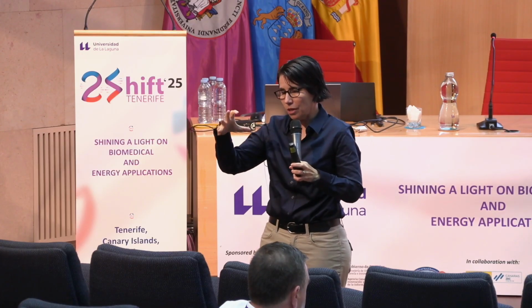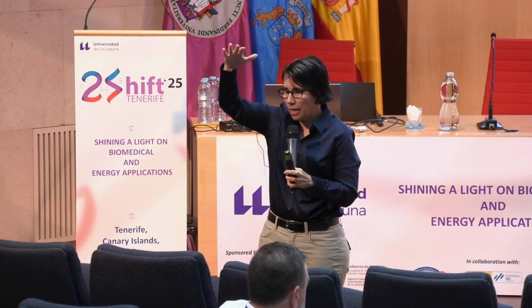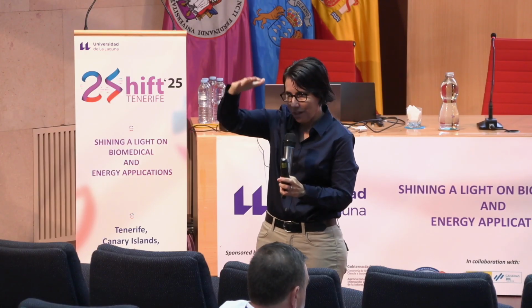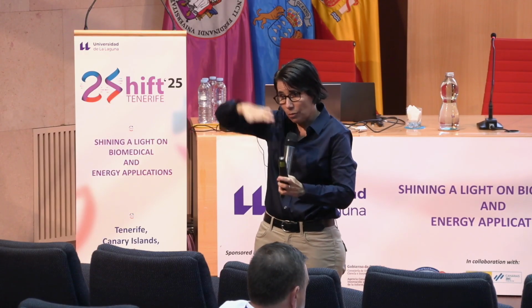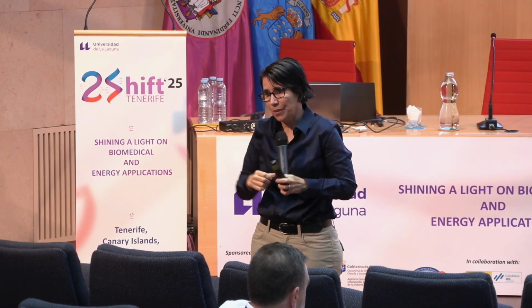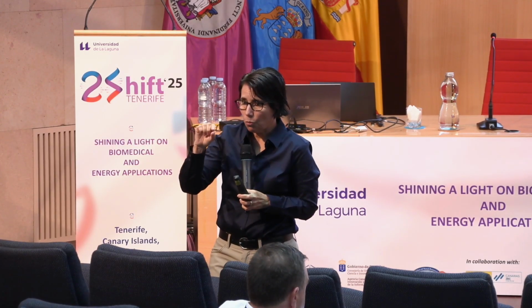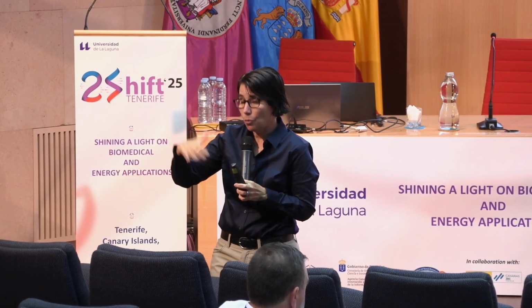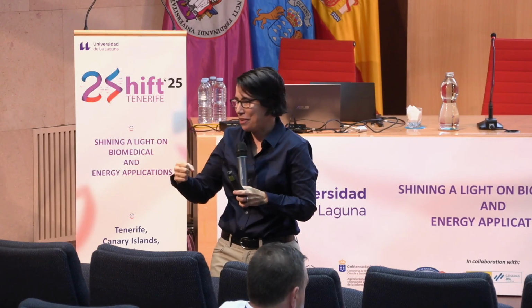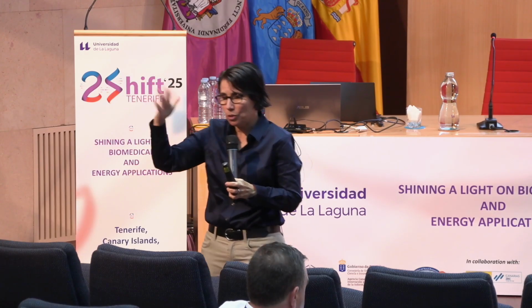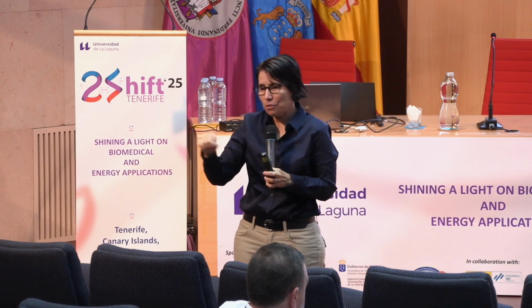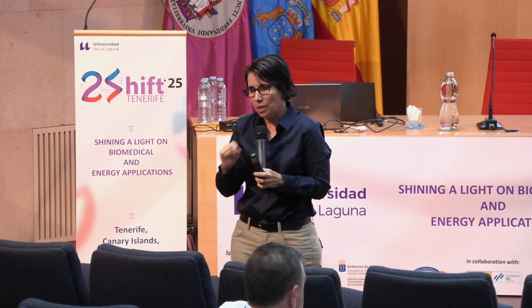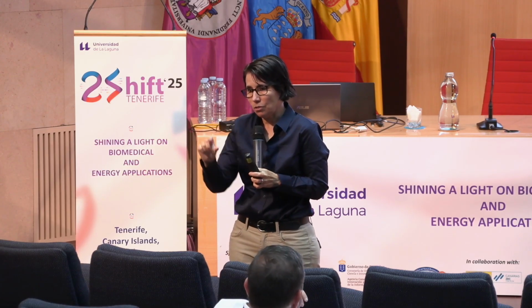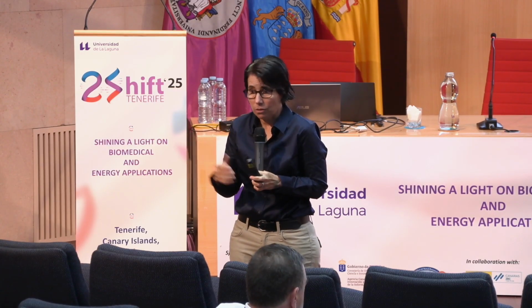If you have a layer of nanocrystals and do this ligand exchange, even if you have a film, you can see the whole thing shrink together. That's happening this way, which is easy to see, and it's also happening this way. But we do select that surface so that the nanocrystals aren't saying, forget it, I'm leaving. We've fought through examples where we had delamination, so we carefully choose the composition of the material. In some cases, we introduce a self-assembled monolayer to increase the interaction with that surface so that we create that misfit strain and don't lose the nanocrystals. Okay, thanks.